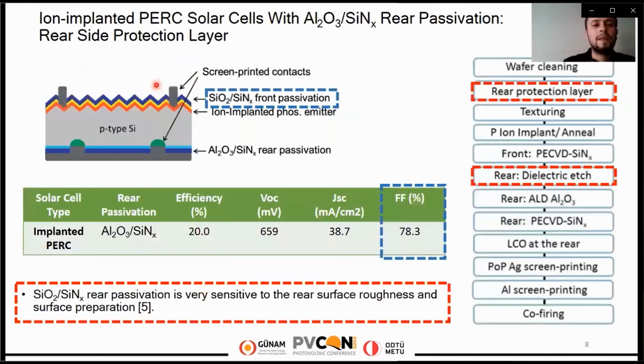This is an accomplished ion implanted PERC solar cell study conducted at ISFH. It seems to be a proof of concept study to show the quality of an implanted emitter, because they included two additional process steps here. One of them is the deposition of a rear protection layer, and the second one is the removal of this layer. They included these steps because they introduced oxygen during the activation of phosphorus dopants.